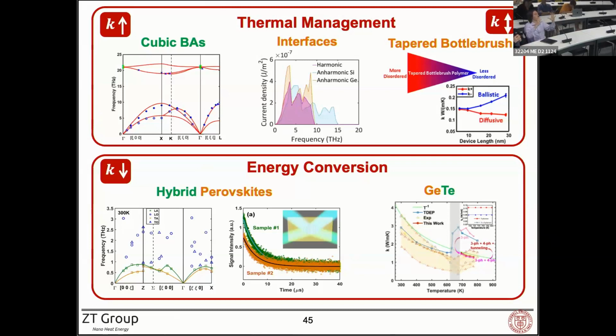So if you sample at a different temperature, you're sampling a different region of the Born-Oppenheimer energy landscape. So if you truncate the potential, so if you say I stop at fourth order, then those terms depend on the temperature because they depend on how much you're sampling. But if you have the full potential, the full infinite series, that will not depend on how much, because it will have an infinite convergence radius around it, and so if you sample very little or sample a lot, the terms of the Taylor expansion are exactly the same.